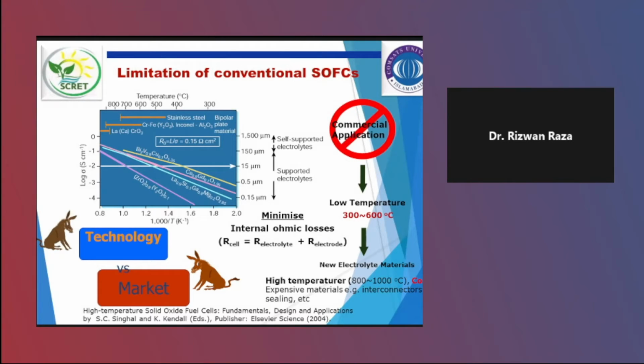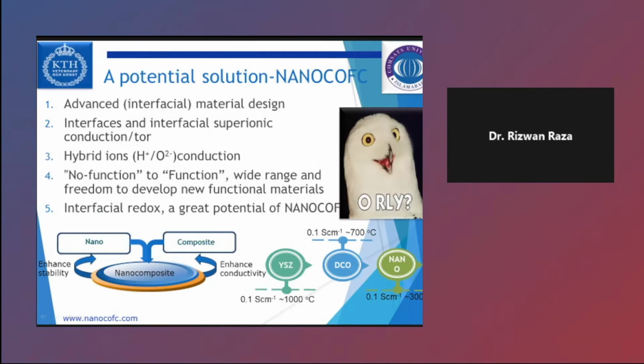For an SOFC electrolyte, there is a benchmark of 0.1 Siemens per centimeter as the ionic conductivity. If the same ionic conductivity can be achieved at low temperature, it would be very good. So that's why there is a challenge to get a low temperature based material. There is a need to develop some materials at this temperature. There was one European project, and I was part of that project at that time, about nanocomposites for fuel cells.